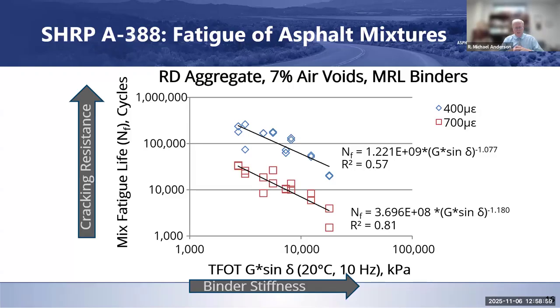It's one of the reasons why, we've heard of the concept of Super Pave 5. There's been a number of people that have talked about that. The idea being that you design it at 5% air voids in the laboratory, and then you compact it to 5% air voids in the field. So you've got a mix that maybe doesn't have as high an asphalt content as what you normally would put in it, which would normally be bad for fatigue. But if you compact it enough in the field, you reduce the ability for it to oxidize as it comes down, and so that lesser asphalt content volume doesn't play as big a role.